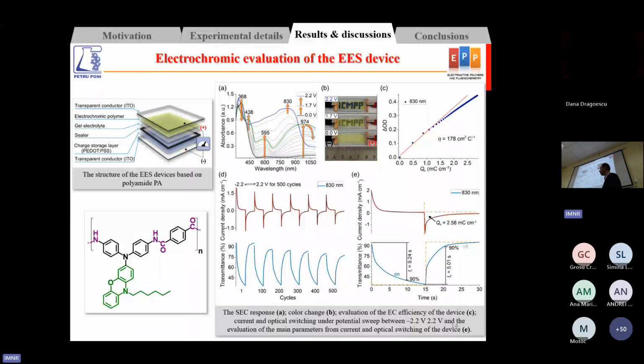After we investigated all polymers, we came to the conclusion that the polyamide would be the most suitable to be tested in a prototype device made in the laboratory. So the device includes a sandwich configuration with the polymer as the anode and the cathode PEDOT:PSS layer as the charge storage layer. The device was subjected to various voltages with increments of 100 millivolts, and the polymer exhibited a comparable behavior to the polymer deposited on ITO substrates.